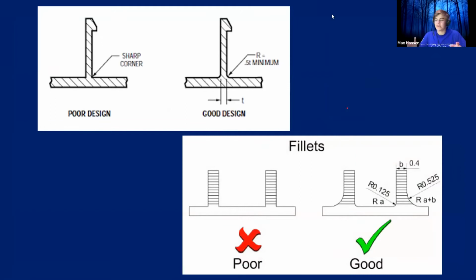So then another look at fillets. In the top, we have a poor design here that has these sharp corners. And on the right side, we have a good design. And on average, for your fillet, you want to have 0.5 times the thickness. So if the thickness of your part is a quarter of an inch, you usually want to have a 1/8 inch fillet as your smallest possible.